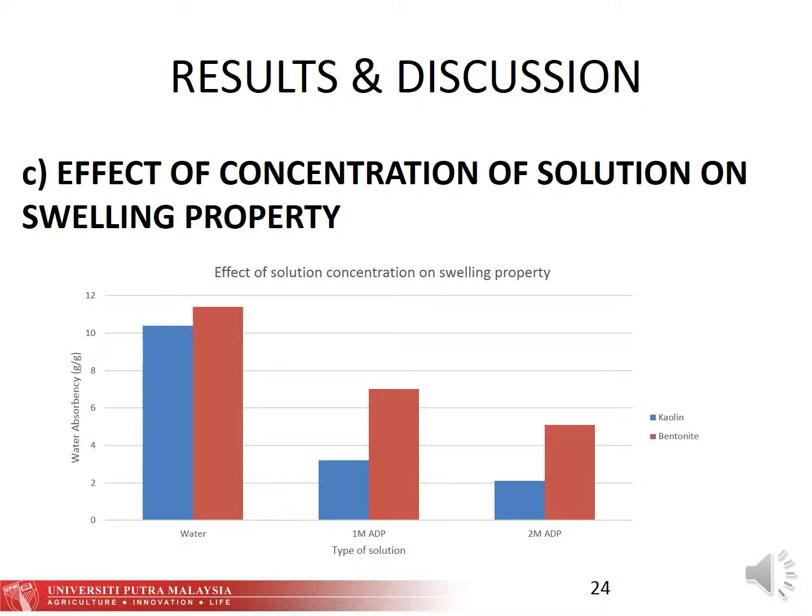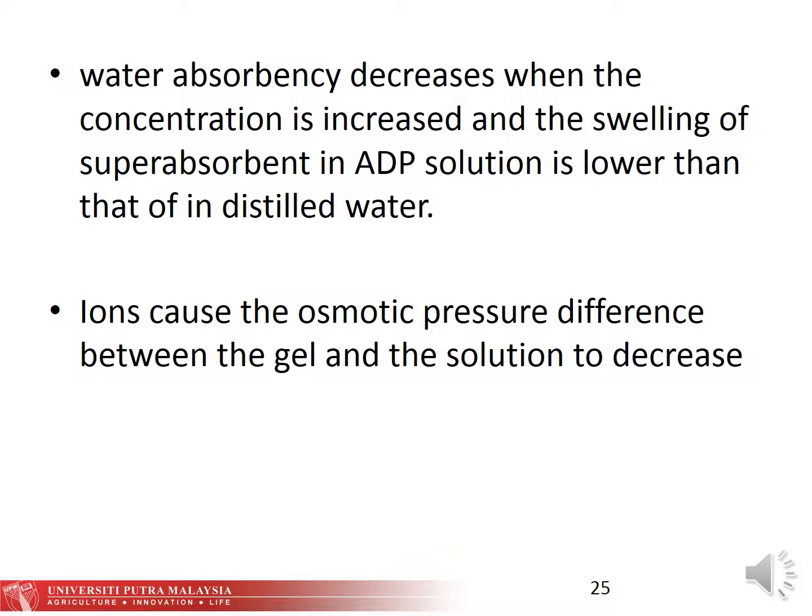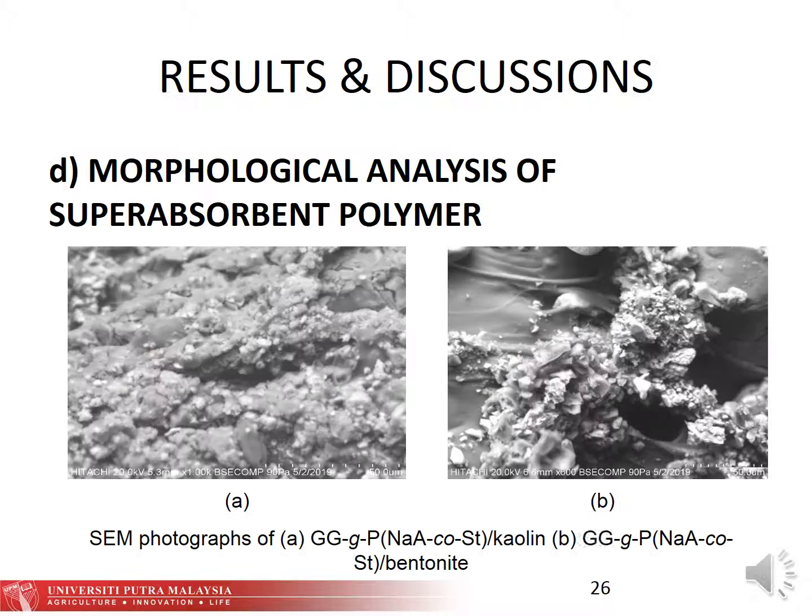For the effect of concentration of solution property, when the concentration of the solution increases, the swelling of the SAP decreases. This is because of the ions present. The ions cause the osmotic pressure difference between the gel and the solution to decrease.